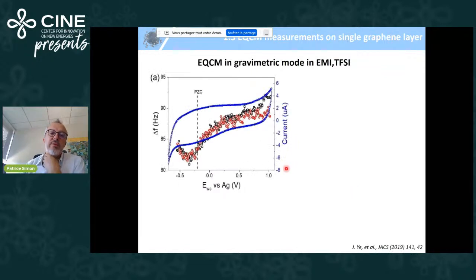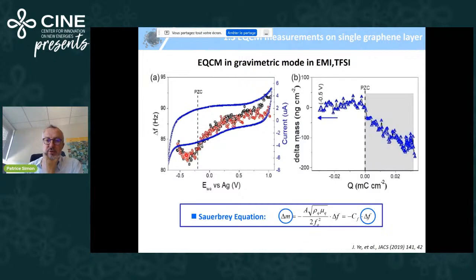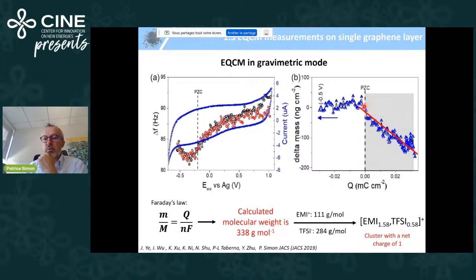And first, what we did was to record the change of the resonance frequency during the polarization. And then we transform, as I mentioned before, into weight change versus the charge. So this is the same single layer graphene in EMI TFSI. What you see is that when you start from PZC, you go to positive polarization, you have weight loss. Weight loss means that you desorb something. You desorb a mainly positive charge. And we found that the slope corresponds to a kind of cluster, which is EMI 1.6, TFSI 0.58, cation. So it's a cluster with a net charge of 1.